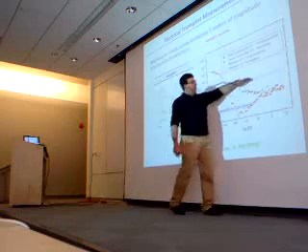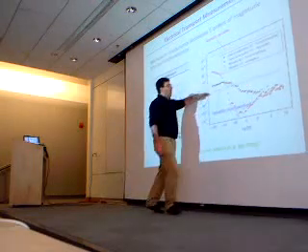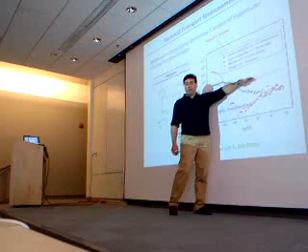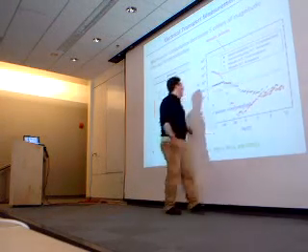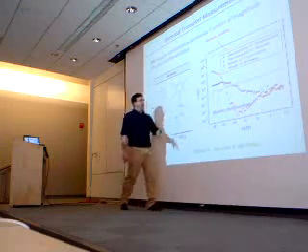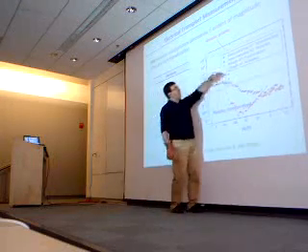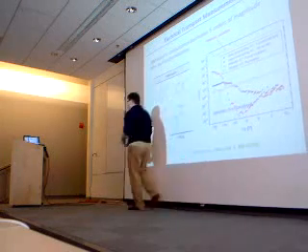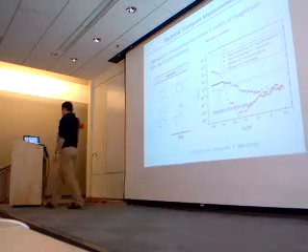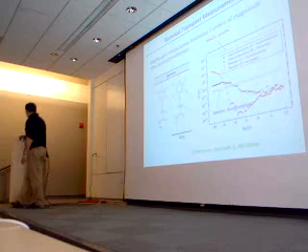What they found was very low conductance, very high resistivity for the functionalized metallic tube, and as soon as it was heated and these residues were leaving the system, it would still be metallic, but with a conductance that was 5 orders of magnitude larger.